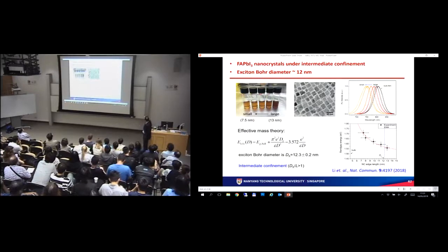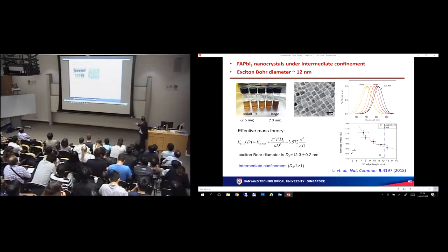Now, the dots that we use are the formamidinium lead iodide dots. We changed this dot system to go to a wavelength around 750 nanometers. This was made by Raihana from Subodh's group. And these dots are in the weak to intermediate confinement regime. So we made different sizes, from 13 nanometers down to about 7.5 nanometers.